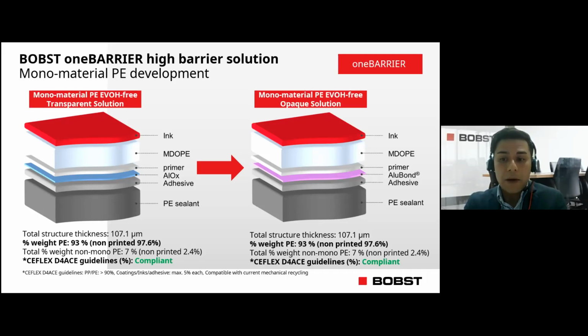Then the One Barrier primer is applied through the BOBST Vision D850 coating laminating machine. AlOx or AluBond is then coated on an EXPERT K5 vacuum metallizer and laminated on our NOVA SX550 with a solventless adhesive, as this would have low thermal impact to PE. The film is then surface printed.